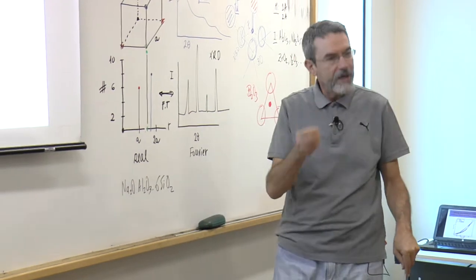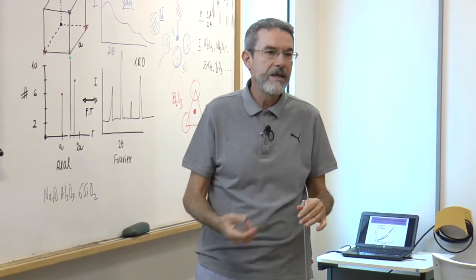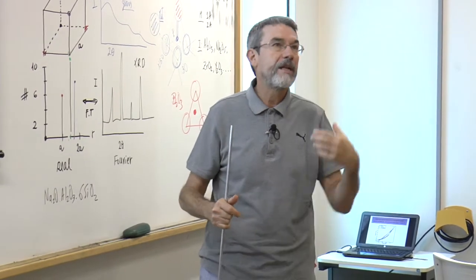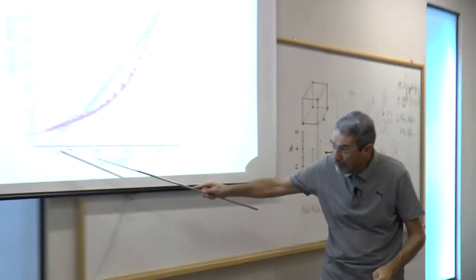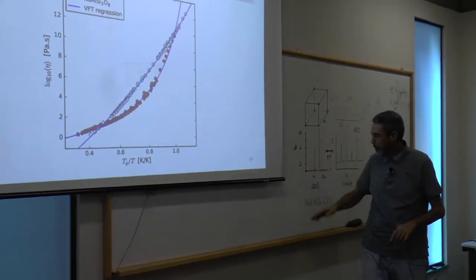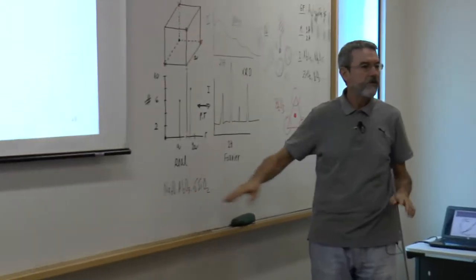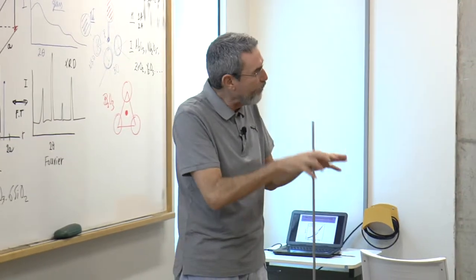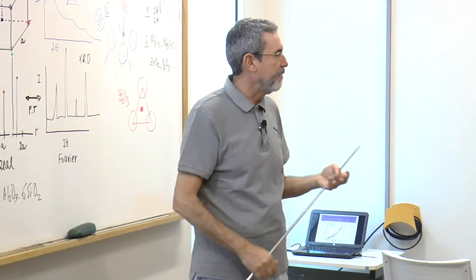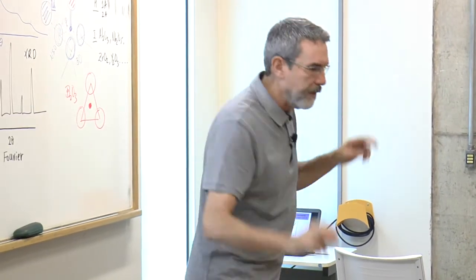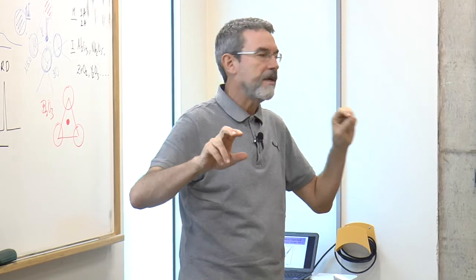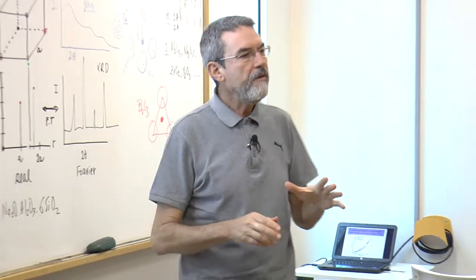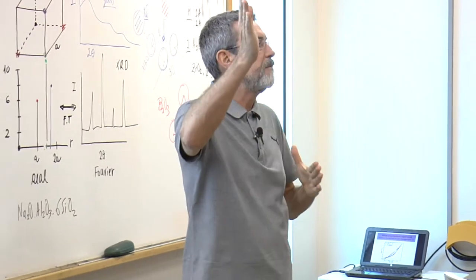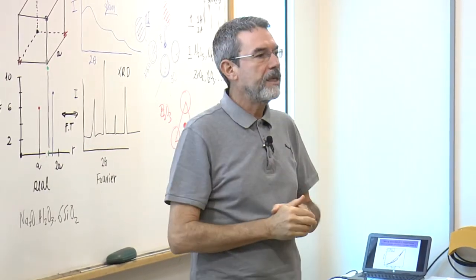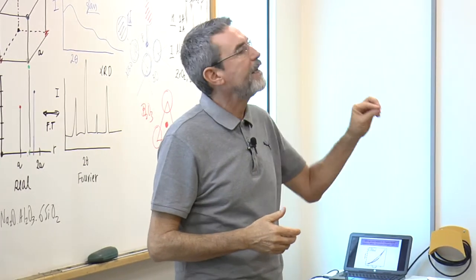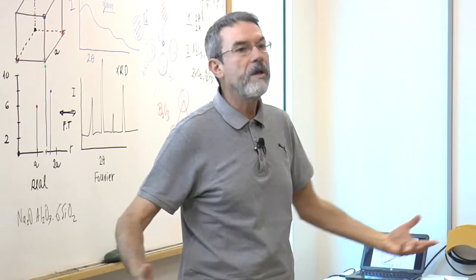It's not perfectly Arrhenian because there are impurities. A real glass has a little bit of iron, a little bit of potassium, a little bit of, you name it, something. So it's not perfectly pure. You can make a perfectly pure glass only in the computer. If you do in molecular dynamics, then you can do a perfectly pure glass. In real life, you never have. Even pure silica, the purest silica, have impurities. OH, sodium, iron. So even pure silica does not have a perfectly Arrhenian viscosity curve. It's a little bit curved because of the impurities. So there is a little bit of non-bridging oxygens in real materials.